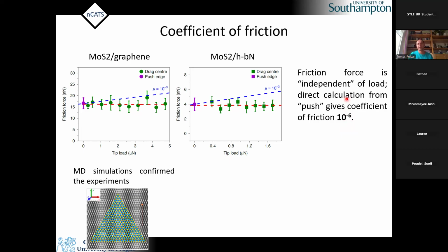And in the paper, we did a lot of work, but we combined molecular dynamics in this case, and a little bit of ab initio simulation to confirm the experiments. And that's the importance of combining experimental work and theoretical work, because in experiment we show this very low friction, but in theory we explain why we get that. And that was really cool.